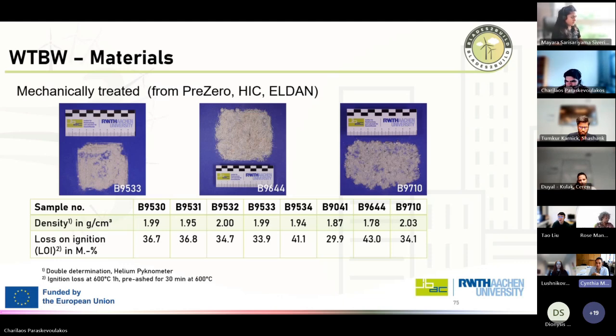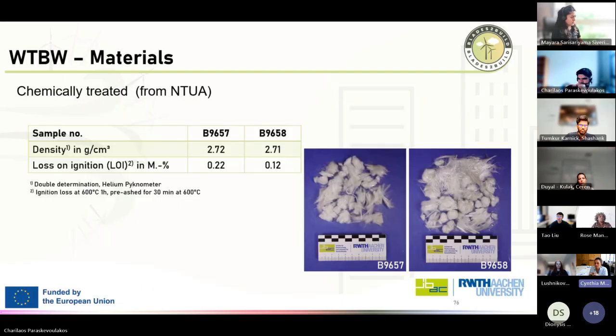So at Aachen, we received mechanically treated turbine blade waste materials from different companies or different preparators, I would say. So in the slide, you should observe different fractions from these mechanically treated fibers. And they differ in density, but also in the loss on ignition content. The higher the loss on ignition content, the lower the density naturally. But we do see some major differences here. Now, in the later slides, I will only present as a comparison the results from the mechanically treated wind turbine blade waste from the B9710. So if you please go to the next slide, that's why I have it highlighted.